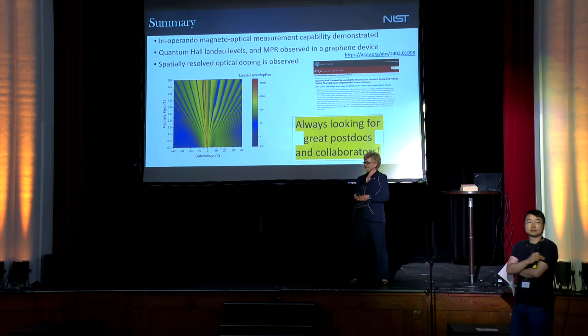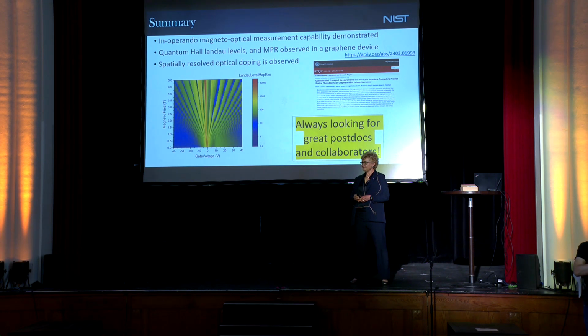Thanks very much. Are these magnetophonon couplings also observed for other phonon peaks, 2D or other, or is it only on G? Yeah, so if the energies of the magnons and the phonons are close, the chance of having more significant interaction goes up as their energies become closer. But we've seen it like 20 wave numbers away, we can still see the interaction. And in the cobalt titanate, we actually see the exciton interacting with both magnons and phonons. So again, the quasiparticle soup business kind of came from that.